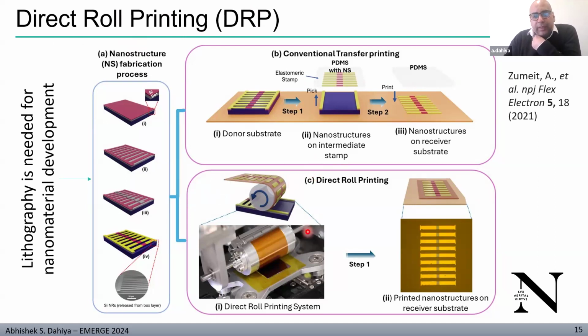In this, what we have done is that we have used a semi-cured polyimide onto the roller, and these nanostructures are defined onto the rigid donor substrates. And when we roll, because of the semi-cured nature, an adhesion is formed between the nanostructure and the flexible substrate, and we can directly print the nanostructure in one step.